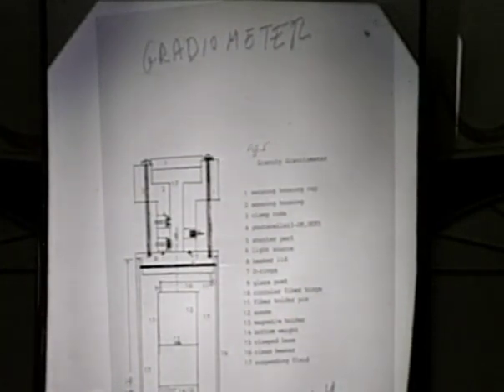Well, that puts fairly good constraints on the temperature control mechanism, but one more point, we're very sensitive to gradients in temperature, so we must have a uniform temperature enclosure as well as having a constant temperature. All right, we were working on that project when the news of the Pons-Fleischmann effect came out, and we easily saw that this would provide us with a calorimeter. Our device would provide an excellent calorimeter for measuring the possible thermal effects. This gradient gravitometer was of interest to oil companies, and so you can understand energy was of interest to oil companies, and therefore we concentrated on the energy part, the heat production part.